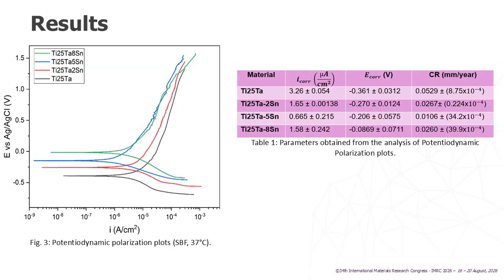After the open circuit potential had stabilized for 3600 seconds, the potentiodynamic polarization curves of the sintered alloys were obtained using SBF, showing a shift in the corrosion potential toward more positive values as tin was added to the materials, and suggesting a possible trend toward improved corrosion resistance, resulting from greater stabilization of the passive layer that these types of materials tend to form.